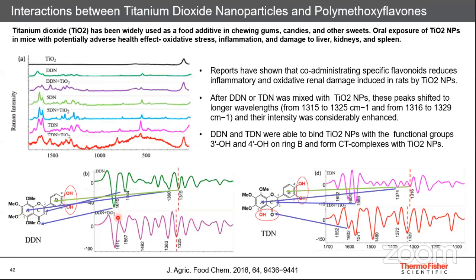Now, when they mixed it with TiO2, what they have seen is there's not much change in these bands. There's no change in the carbonyl frequency, no change in the frequency of the double bond that is attached, and also not much change in the frequency of this aromatic ring. But what they have seen is a large shift, almost a 10 inverse centimeter shift, of this band, or peak in the Raman, which is associated with this ring.